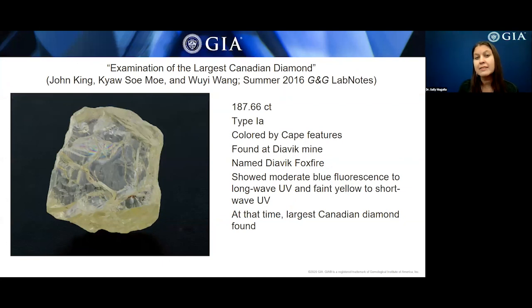This pale yellow type 1A diamond from the Diavik mine weighed 187.66 carats and was the largest Canadian diamond mined at that time. The Diavik mine, located in the Northwest Territories, about 200 miles northeast of Yellowknife, began production in 2003. This diamond was shown to be colored by Cape features and had moderate blue fluorescence to long wave UV and faint yellow fluorescence to shortwave UV.